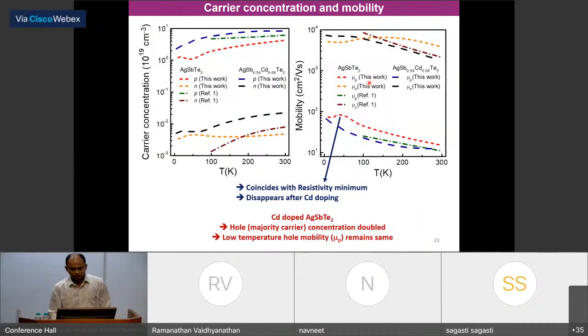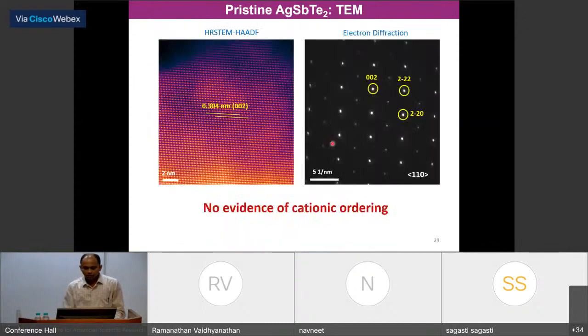So let's see, this is the detailed carrier concentration and mobility data measured by extensive low temperature PPMS experiments, where we have shown the increase in carrier concentration by cadmium doping. That's what we proposed, and we see that. Although the carrier concentration increases, mobility does not decrease with cadmium doping, because cadmium actually delocalizes the electronic states in ordered AgSbTe2. So now you can ask me a question, can we see this atomic ordering by eye?